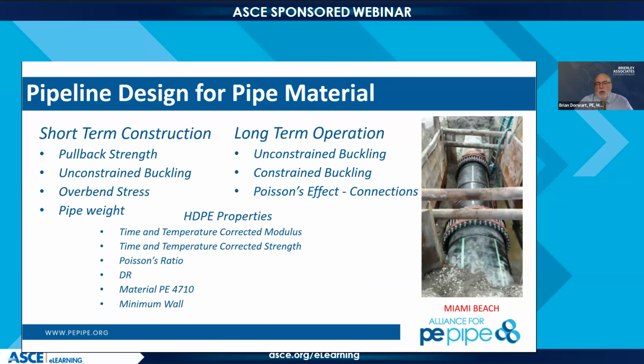The only other one would be more of a slip lining or a bursting with HDPE. Again, you got your material around you when you're bursting it. It's going to be left in the ground. We found that you can use PVC, but with HDPE, it takes a tremendous amount of abuse if you have a problem product, that host pipe that you're trying to burst. The HDPE comes through, even if it gets some scratches on it, it's just not a big deal, mainly because it's a gravity pipe, so scratches you don't really worry about, only in pressure pipes. Then there's certain rules for depth. So with that, some of the surface problems and shallow installations, I'll let Peter discuss that a little bit.